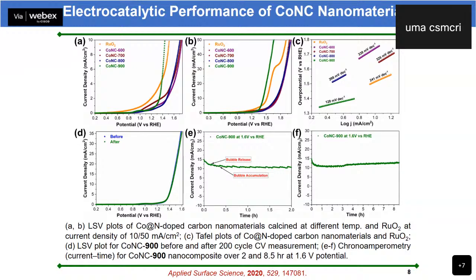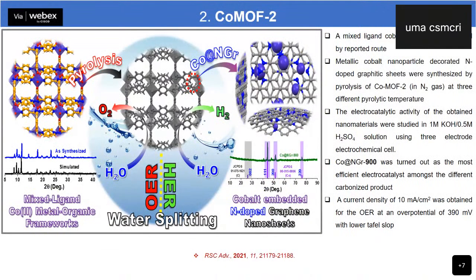Then we also performed LSV after 200 cycles of CV, and the outcome values are comparable with the initial. Then chronoamperometry was performed to see the stability, and the material was stable up to 8 hours without any significant loss of current density. Then in continuation of the previous work, cobalt MOF 2 material was prepared. In this material, the organic moiety of the MOF is different and contains a lower concentration of heteroatom, basically nitrogen atoms.